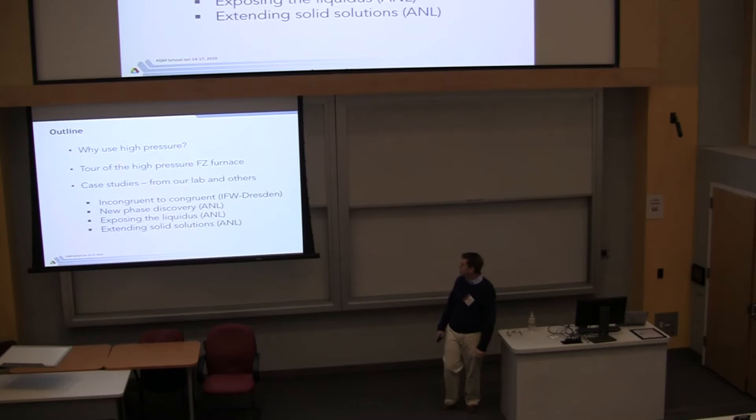And the reason you have to go to these high power lamps is because this fluid, there's convection and there's heat transfer in this system. And so a lot of efficiency is lost due to this environment that you're growing in. So you have to have a lot of power to be able to get there. So you use a big bulb. It turns out it's a projector bulb. That's what they use at the movie theater.